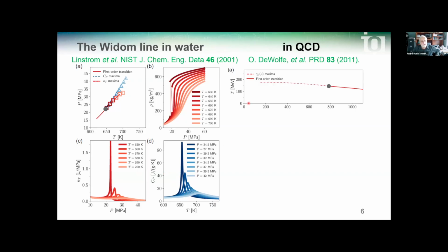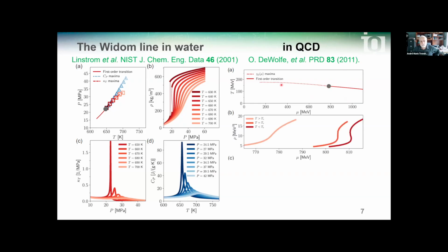In a completely different field, I'll come back to it soon, like quantum chromodynamics, theory suggests in the temperature-chemical potential phase diagram a critical point at the end of a first-order transition between the quark-gluon plasma and hadrons. The dotted line is a Widom line. The plot of the density of that fluid as a function of chemical potential is very similar to the density versus pressure plot in water. And the derivative of that plot, which corresponds to compressibility, has a maximum upon crossing the Widom line.